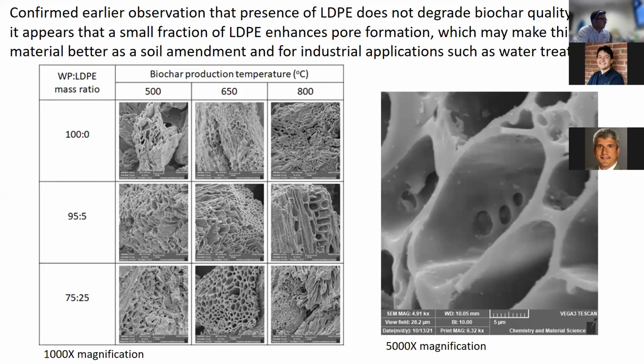He provided a lot of data, but just to highlight what we found, these are scanning electron microscope images of the biochar made with a combination of wood pellets and low density polyethylene at 3 different mass ratios. The top row of images corresponds to the pure woody biomass produced at 500, 650, and 800 degrees centigrade. And then as we move down, we have biochar produced with 95% biomass, 5% LDPE, and then finally 75% biomass and 25% LDPE.